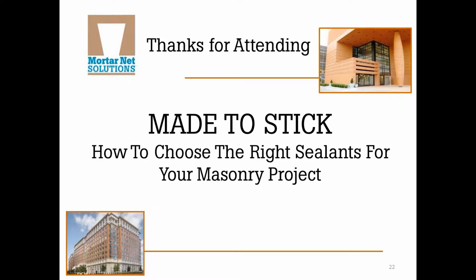Okay, we have another question. What is the life expectancy of polyether? Polyether and modified polyethers, it depends on how much UV exposure they get. Mortarnet MPE-1 is rated for up to 12 years if it's exposed, and it'll last a lot longer than that if it's not exposed. The best thing to do is check with the manufacturer. They do vary a bit, and it does depend on the conditions.